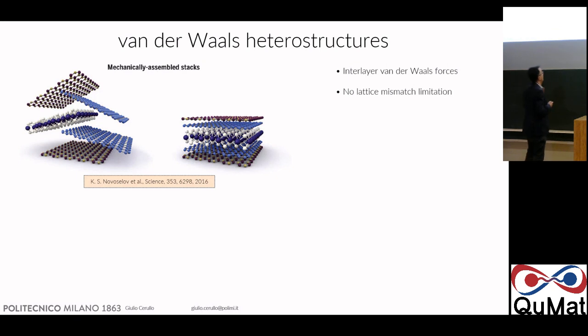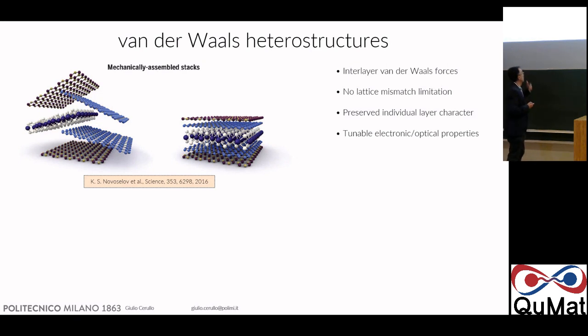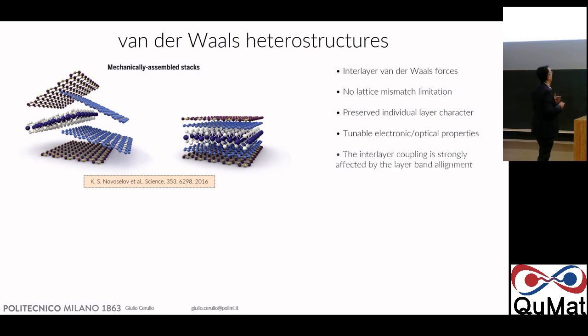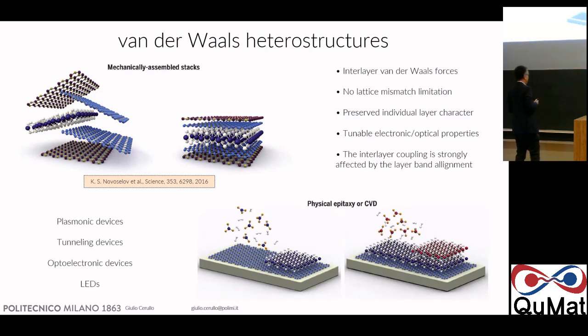So you don't have lattice mismatch limitations, and each material preserves its individual character, but now you can get new properties which are tunable according to the order of the materials, but also you have an additional degree of freedom, which is the twist angle between the two materials. So the layer band alignment, but also the twist angle is quite important. So it's a very rich field, these van der Waals heterostructures.